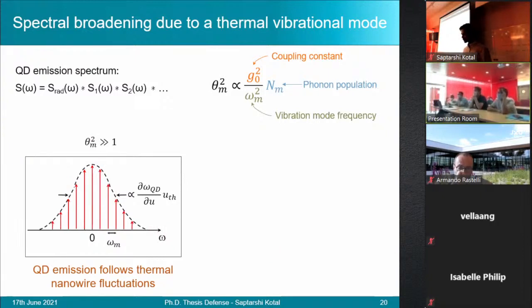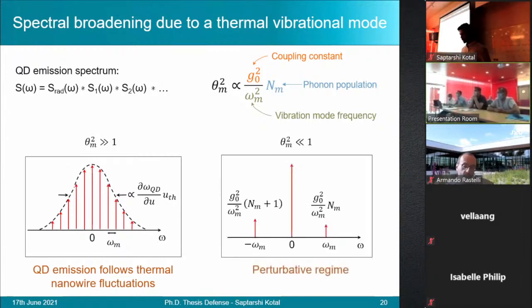In other words, in this case, the quantum dot energy somewhat adiabatically follows the motion of the nanowire. Now, this regime is generally governed by the low frequency modes. Next, we consider when theta m squared is much smaller than 1. Here we name this the perturbative regime.